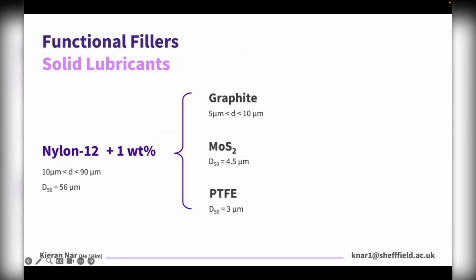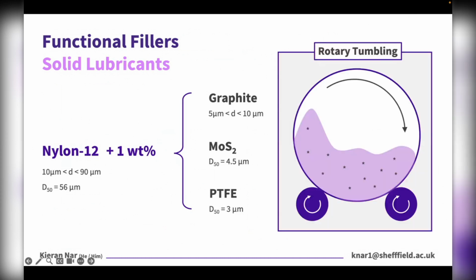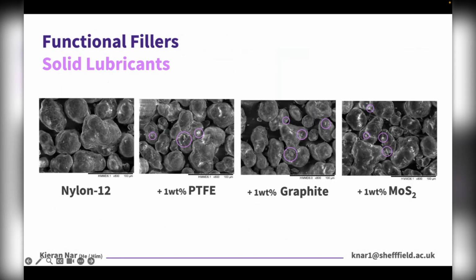More specifically, we individually included 3 different solid lubricants: PTFE, graphite, and molybdenum disulfide, into 3 different nylon 12 powders in 1% weight loadings, and incorporated them into the nylon powders by a very straightforward method of rotary tumbling, or rotary blending, as you can see. As these SEM micrographs indicate, which might be a little bit difficult to see on your screens, we were able to identify that these solid lubricants were actually in the nylon 12 matrices we were evaluating, and qualitatively the results showed that these solid lubricants were well dispersed and showed very little signs of agglomeration.